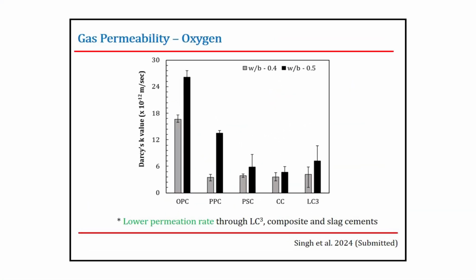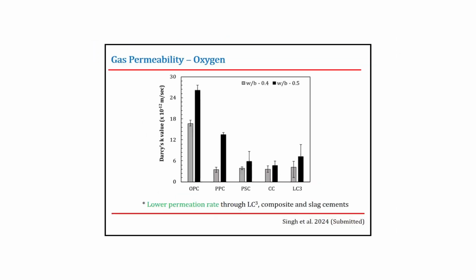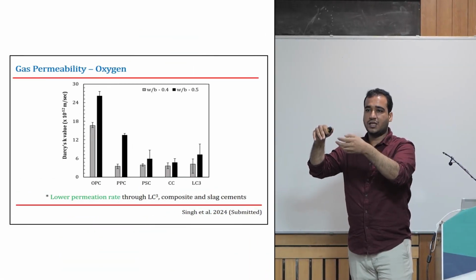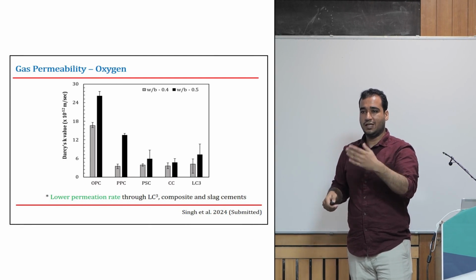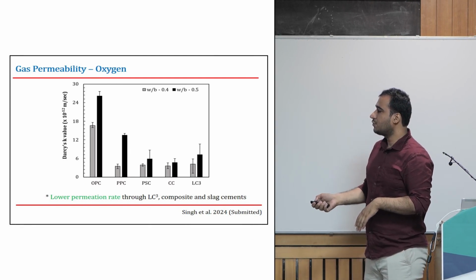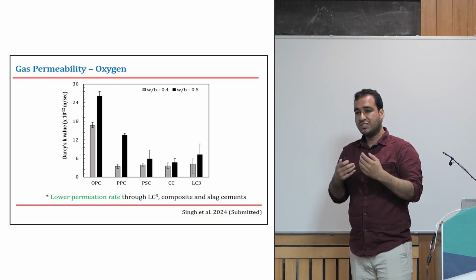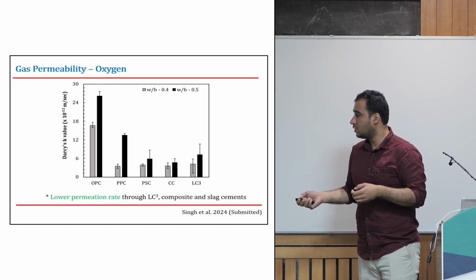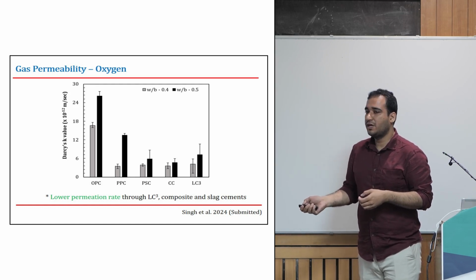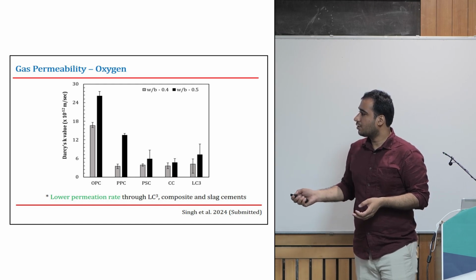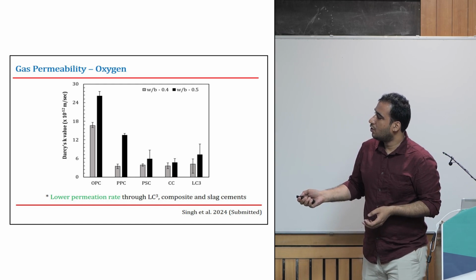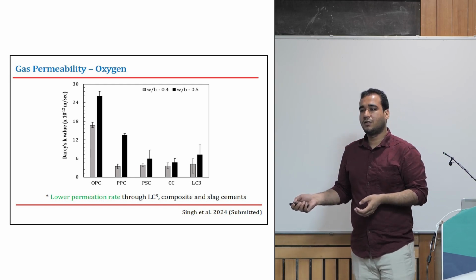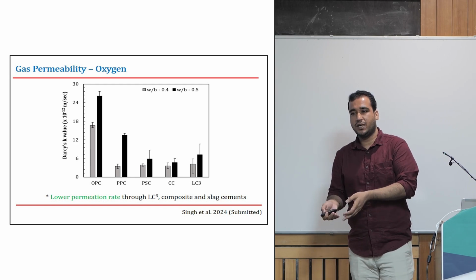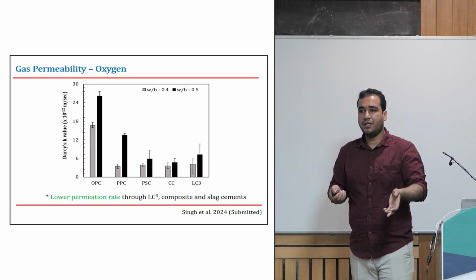Now I was talking about gas permeability. For performing the gas permeability test, what we do is we dry the concrete, and then under a pressure we observe the loss of the pressure of oxygen or any other gas, nitrogen, after a certain time over the decay. It's a falling head type of test. You see, in these types of systems, blended systems which show a nice pore refinement and have less interconnectedness appear to give a very low value of Darcy's K value. So you would think that if carbon dioxide is getting inside at the same rate, probably we are having it better in the blended systems.